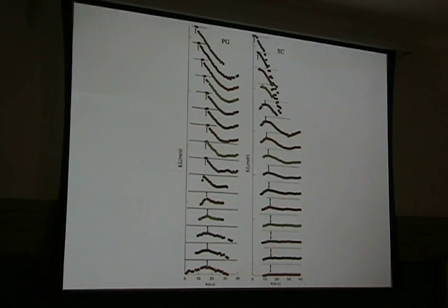Now here's a pseudogap. And you see that the dispersion is just directly going through the Fermi energy. There's no sign of bending. Only when you get to the pseudogap, you start to see back bending, the same as here, okay? Exactly the same. So there's this big signature that there's some mixing going on between maybe particles and holes or particles and particles, we can't tell. But certainly, this is just going straight through the Fermi surface. This is not an arc, because then we would have the same thing here everywhere.